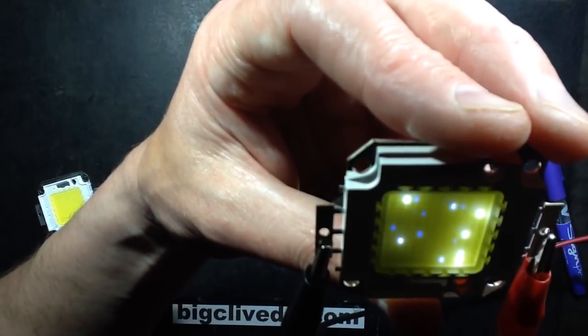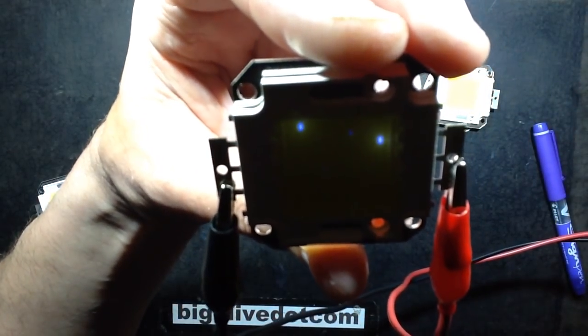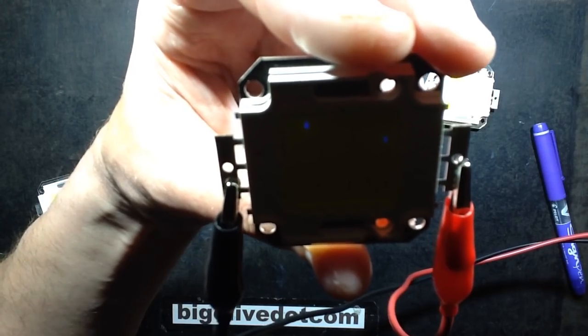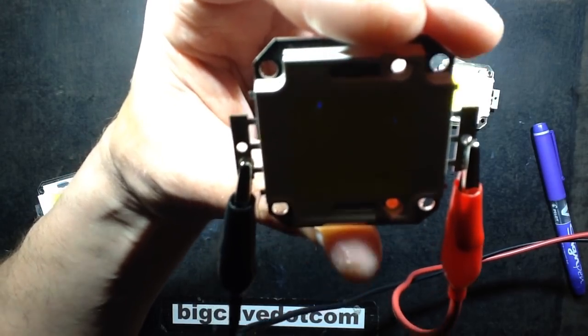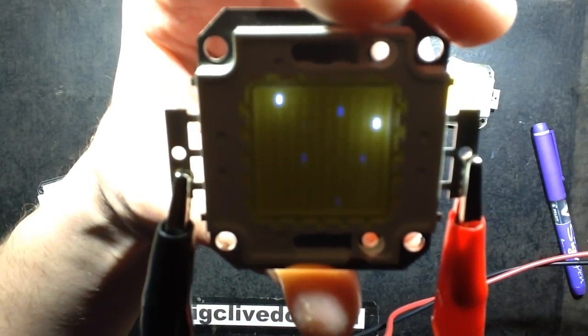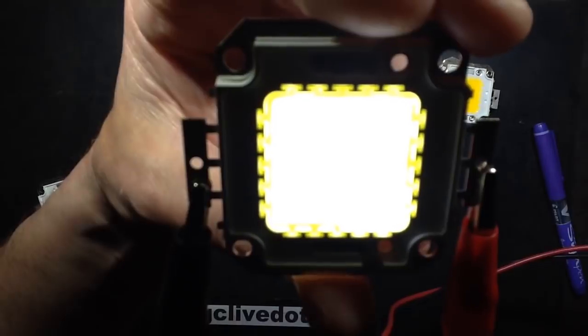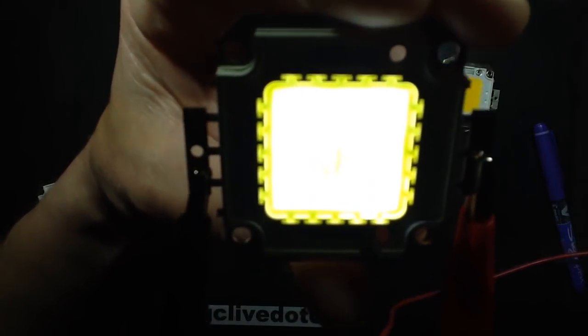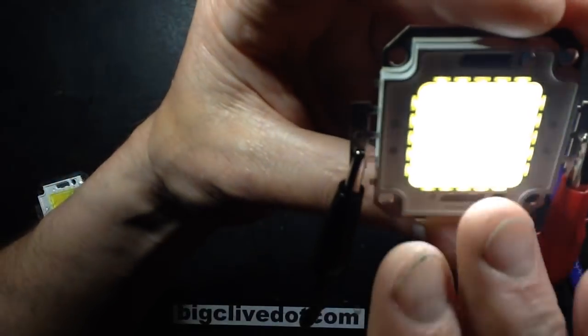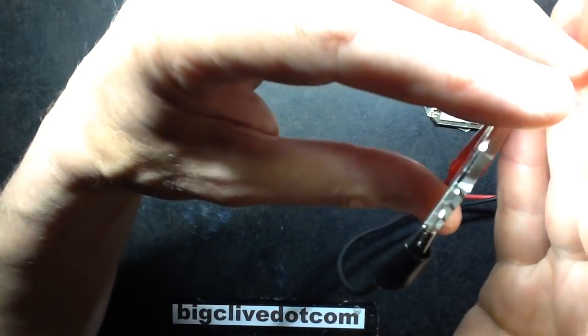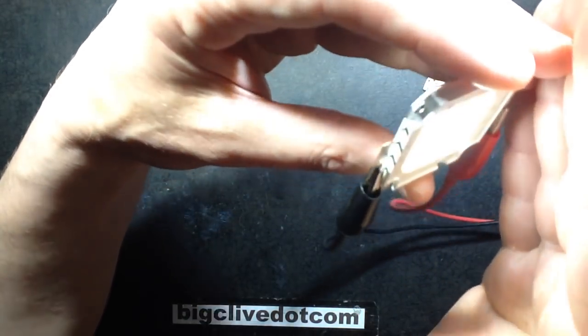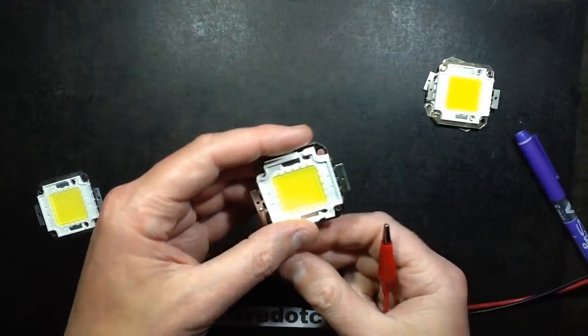Let's see what's the lowest voltage when they're lighting. They're glowing at 9 volts is when some of them are starting to light and you're just getting individuals lighting. And as I turn it up to the point that it's actually drawing a modest current, let's do the 20 milliamps. It's 21 volts 20 milliamps, half of them are not lit and the output is just nothing like the other LED.